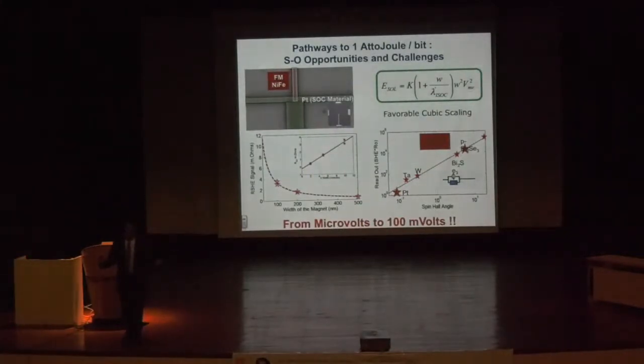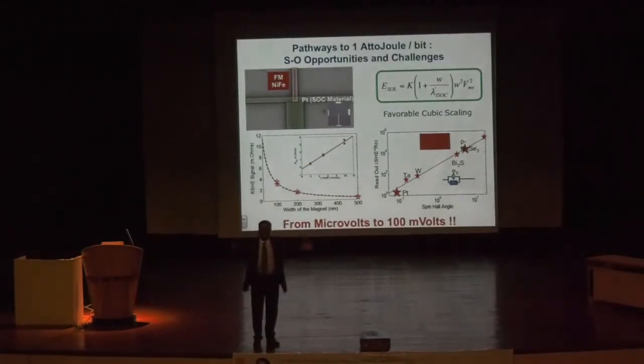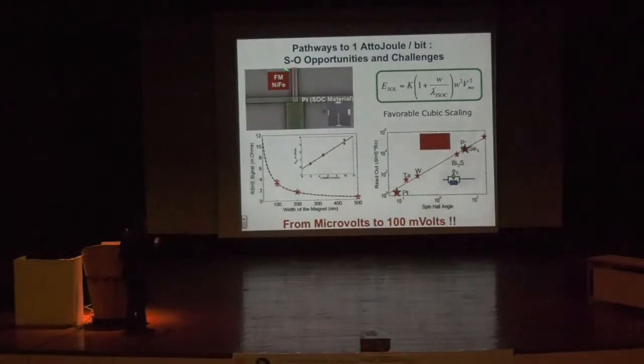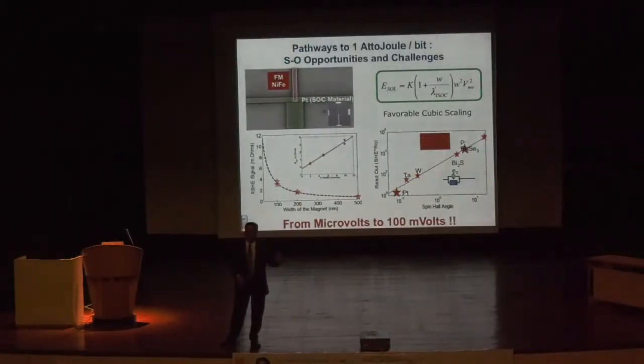On the other side, the challenges are even tougher. That's why when I was talking to some folks this morning about bismuth selenide, bismuth telluride, materials which have very large spin-orbit coupling, if you think there are some fantastic challenges, here's one of them. This is just our standard inverse Rashba device. Basically, we have permalloy as a ferromagnet and a material with large spin-orbit coupling. And the experiment is basically to measure this spin-Hall angle, which translates to the spin-Hall voltage, which typically today is of the order of microvolts, maybe 50 microvolts. We need to get to 100 millivolts, several orders of magnitude larger values of the spin-Hall voltage. How does one go about doing this?